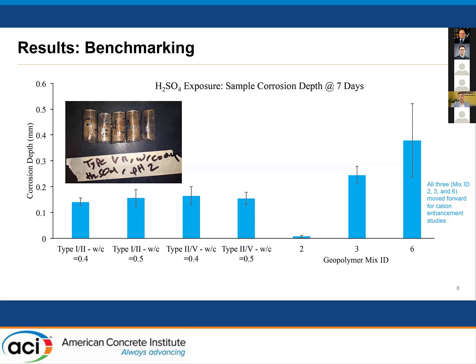So as I mentioned, previous research in my lab by my PhD student, JP Javadhan, indicated to us that when we dope the geopolymer cement with specific cations, we could actually stabilize the sodium aluminosilicate hydrate, the N-A-S-H gel, upon exposure to sulfuric acid. So the question for us was, well, which cations would work best?